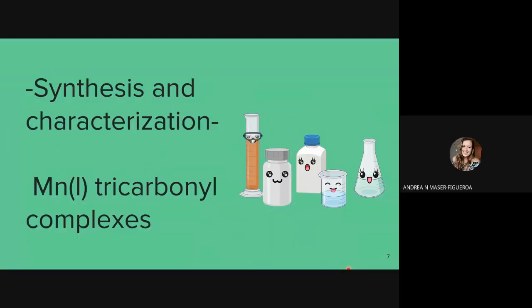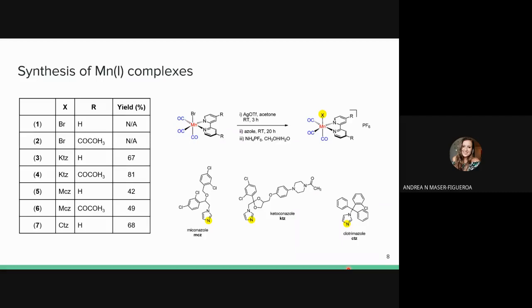So the aim of the researchers was to explore the impact of azole drug coordination to stable manganese tricarbonyl complexes. They did so first by synthesizing their compounds of interest. They treated the manganese tricarbonyl complexes that were either 1 or 2, as seen on the table. They would substitute the bromide, and then afterwards would do the addition of the azole ligand. They followed this by column chromatography, and they stated that the end result, the complex, seemed air and moisture stable. They also obtained relatively moderate to good yields in their synthesis.